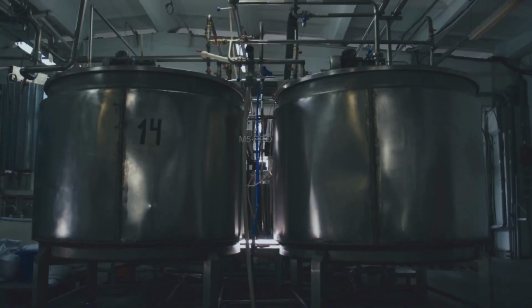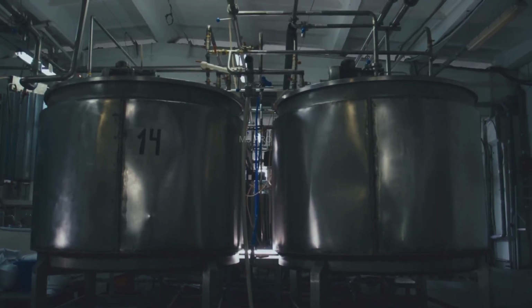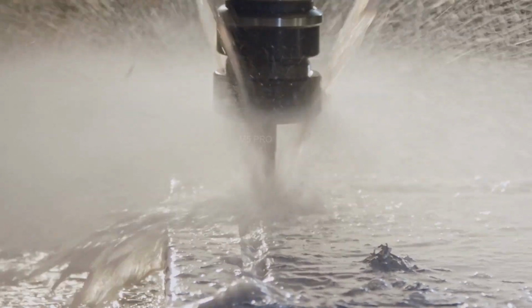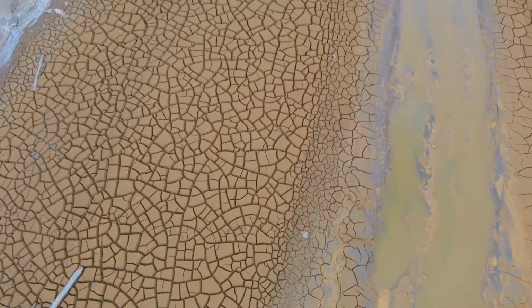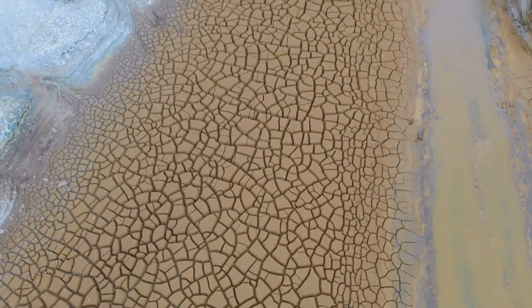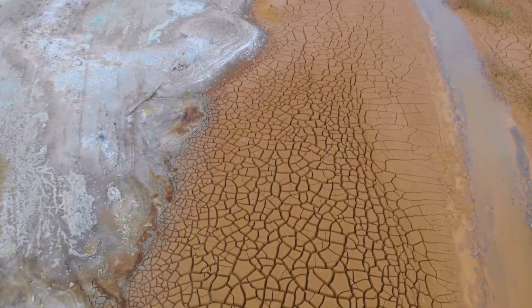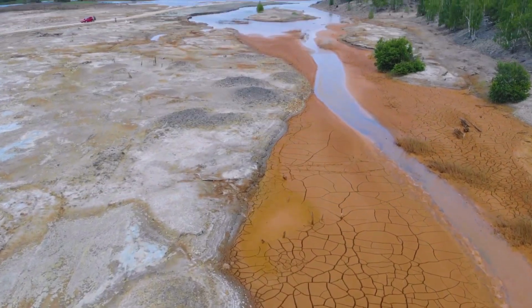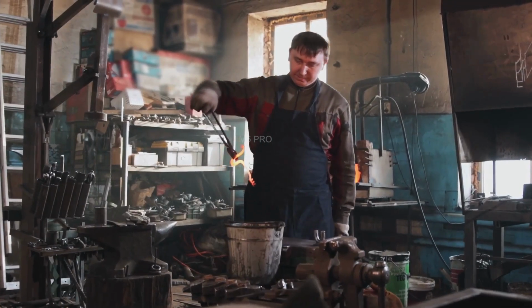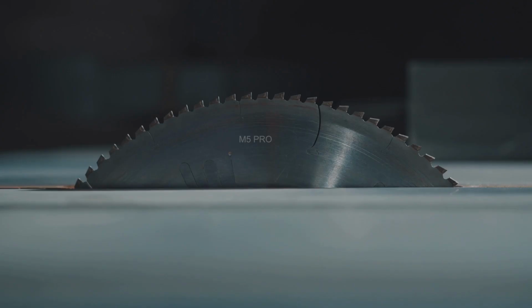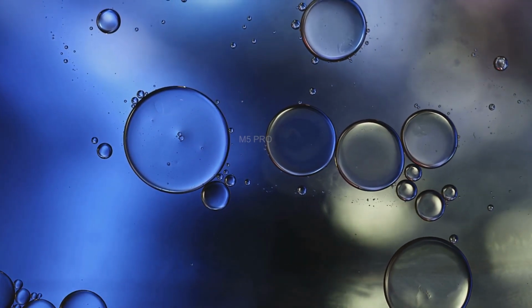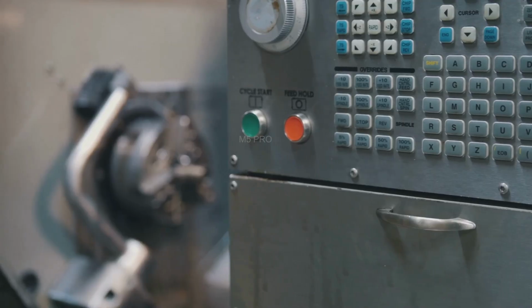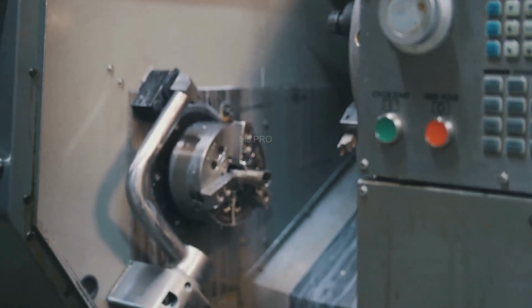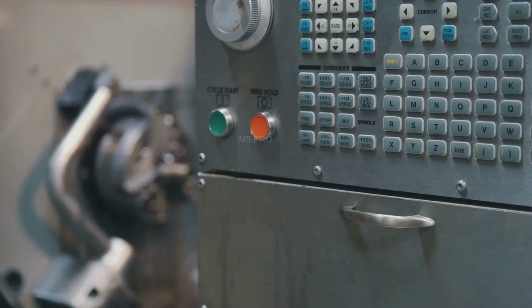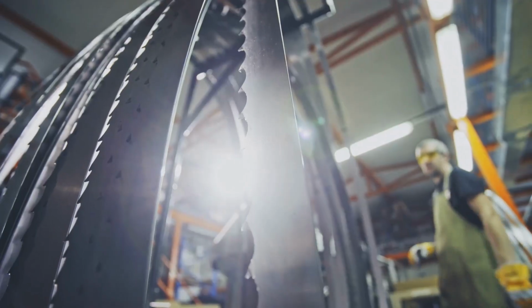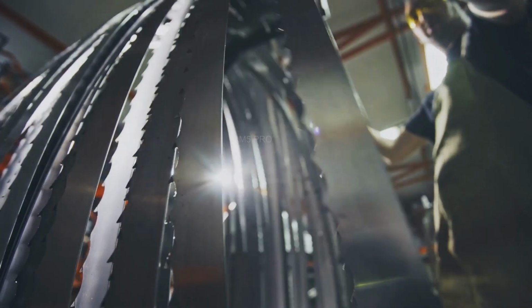The choice of quenching medium, in this case oil, is extremely important. Water cools very fast, which can create immense internal stress and cause the blade to warp or even crack, especially with a thick blade like a cleaver. Air cools too slowly and the blade wouldn't get hard enough. Oil provides a perfect middle ground. The temperature of the oil itself is also carefully controlled to ensure every single blade is quenched under identical conditions, guaranteeing consistency across the entire batch.